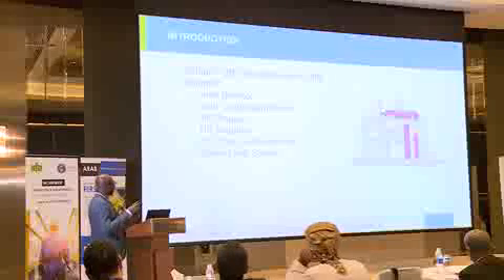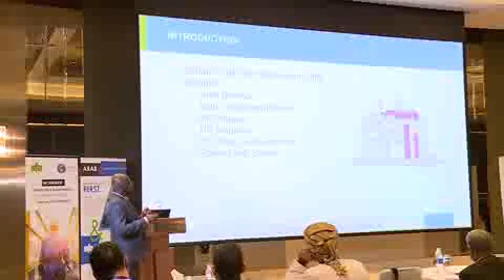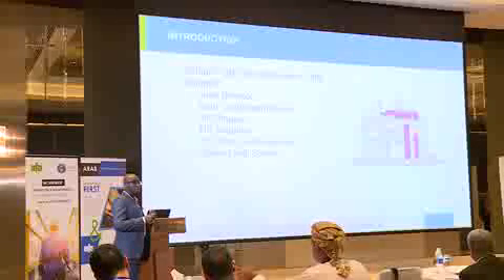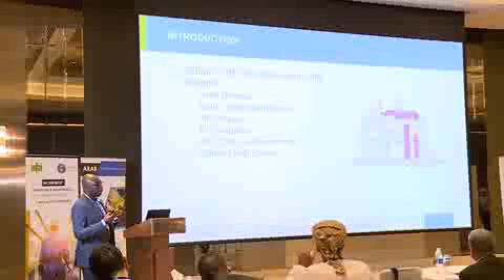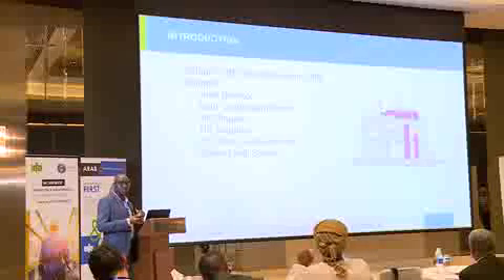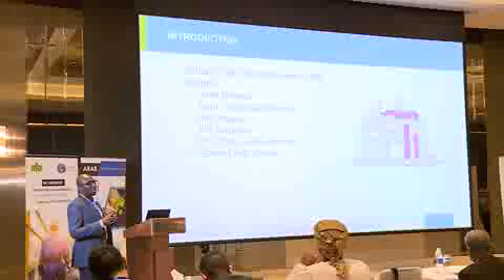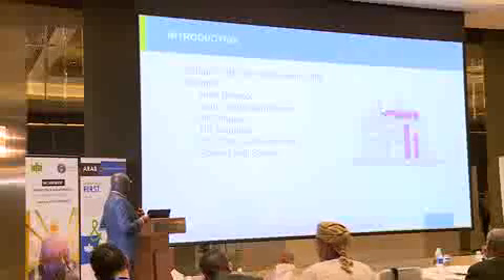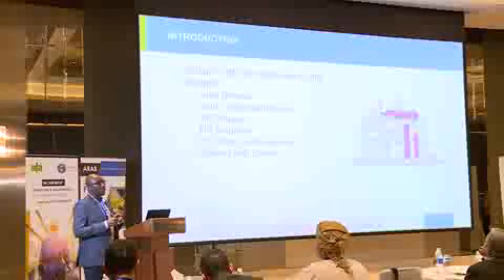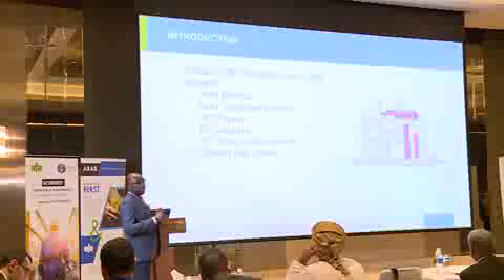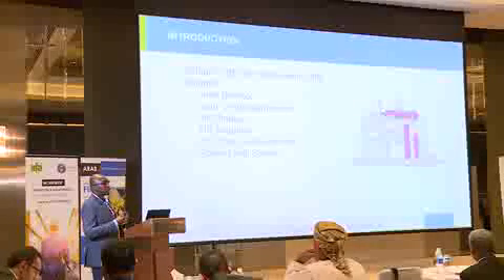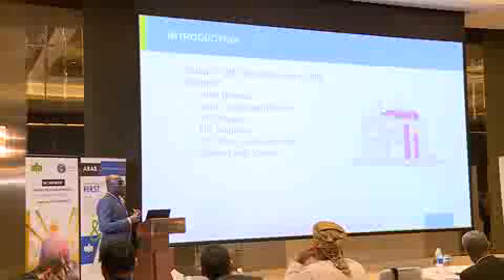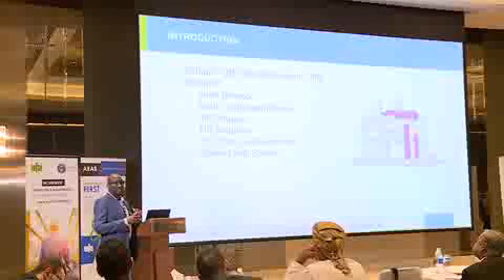So if we go back in the history, actually the commercial production of urea became possible with two things. First, the development of the 316L urea grade material, plus passivation of this material with the addition of oxygen. So in the 70s, Stamicarbon, for the first time, teamed up together with our materials development partner, which is Sandvik, a specialty steel manufacturer in Sweden, to come up with a material that will be better than the 316L urea grade in terms of corrosion. This material is the 25-22-2 or 2RE69 as is known.